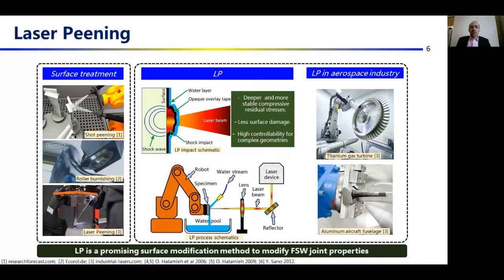Surface treatment methods have been utilized to improve the mechanical properties of aerospace components such as shot peening, roller burnishing, and laser peening, among which laser peening induces deeper and more stable compressive residual stresses with lower surface damage and high controllability. In this process, the high energy laser vaporizes the sacrificial coating layer on the material surface and turns it to a rapidly expanding plasma, which is then confined by a transparent layer to amplify the laser shock pressure.